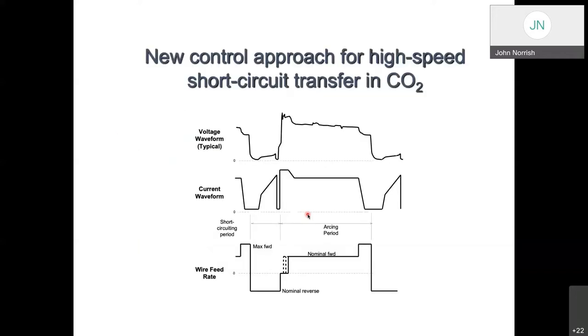We actually developed, and this is an example of industry pull, if you like, the use of that process for welding of pipelines. And it worked particularly well for root runs in pipe, but the problem was that it was much slower than the alternative processes that the pipeline industry was used to. This is usually manual metal arc welding with cellulosic electrodes.